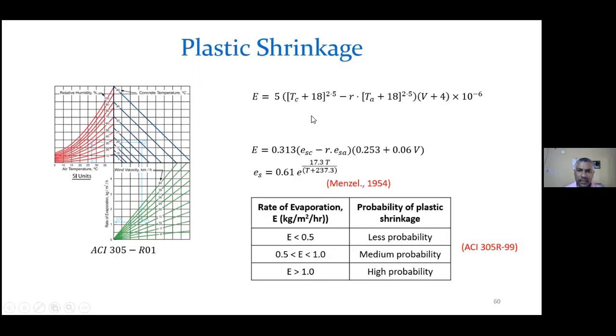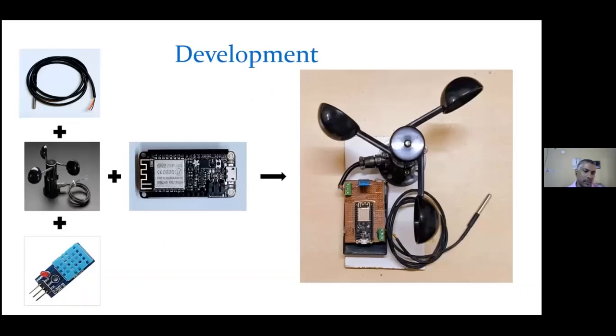So we can measure this evaporation rate through these indirectly measurable parameters, and then we can check whether it is growing, if it is more than 1 kg per meter square per hour or more than 0.5 kg per meter square per hour, and we can take corrective action, right? And for that, I just wanted to skip some slides. Here, this is the sensor to measure wind velocity. This is the same sensor, DS18B20, to measure the concrete temperature, and there's another sensor which measures both relative humidity and the atmospheric temperature. So we have put it together with the same ESP microcontroller and made a system for that.